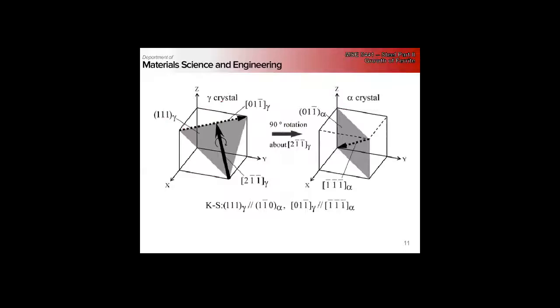Now this Kurdjumov-Sachs relationship, I said it's going to form preferentially with one of the two grains, but this is a very low energy relationship. It maintains that the close-packed directions don't actually change. This is a low energy interface that has virtually no mobility.